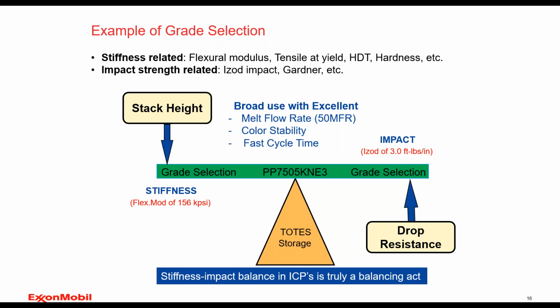What I show here is that we have in the yellow triangle totes or storage bins that somebody's asking for a grade recommendation for, and ultimately the mindset of myself or a molding engineer at our customer would be what's important. And what's important in this case is the stiffness, which is typically measured by flex modulus or the tensile, the HDT or hardness values. They all go hand in hand, correlate in the same direction, versus the degree of impact strength, which is measured by the IZOD impact, which is a notch sensitive type method of impacting, and then Gardner impact, which is blunt force. Both hand in hand can give you good feedback. If you're looking at one versus the other, it can be a little bit tricky.